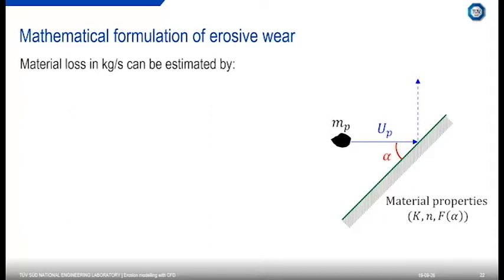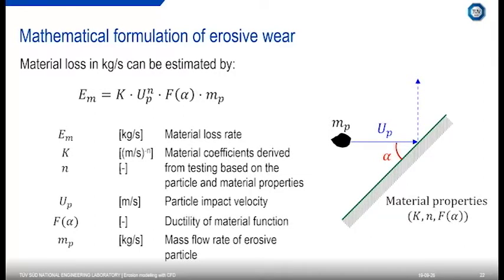So here we can estimate the material loss through this equation, and these parameters are shown on the right-hand side. So we have a particle coming in, so that will have a mass flow rate, mp, that will come in at a velocity, up, hit the wall and rebound, and that will come in at a particular angle and impact our material. So we need to know our material properties, K, n, F of alpha, our particle velocity, our impact angle, and of course the mass flow rate of the particle, which we have here.